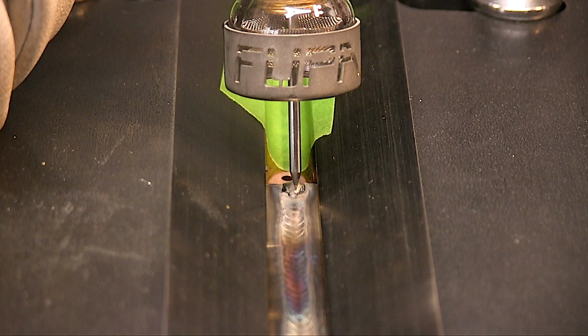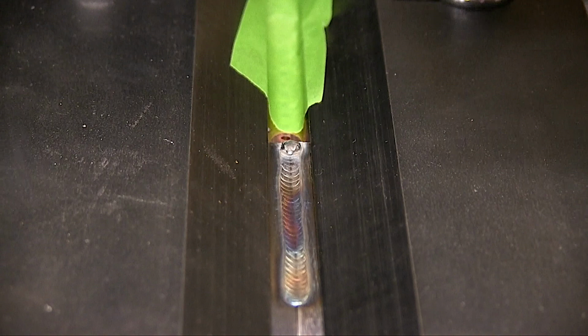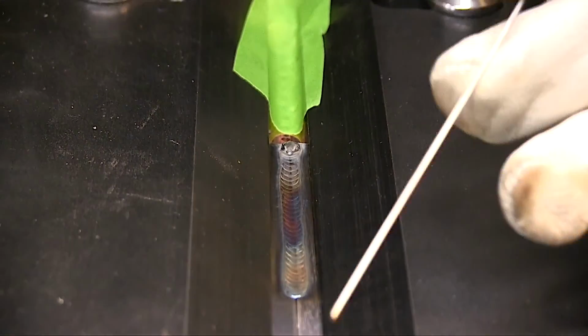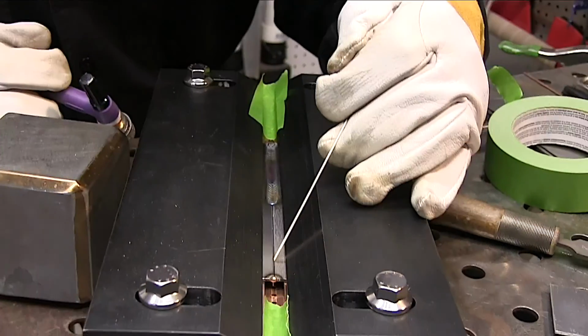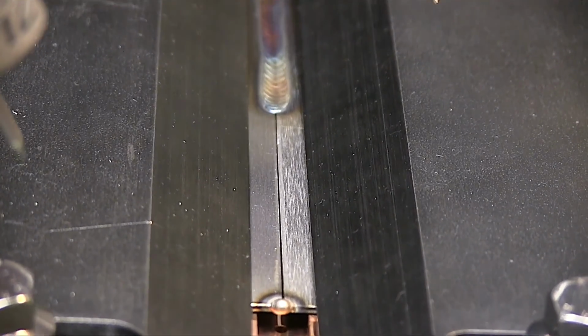And that works really well for not only a test like this, but it works for actual aircraft parts when you're welding a crack out to the edge of something like that, and then you have to maybe blend it off flush afterwards. It's just really a good technique.